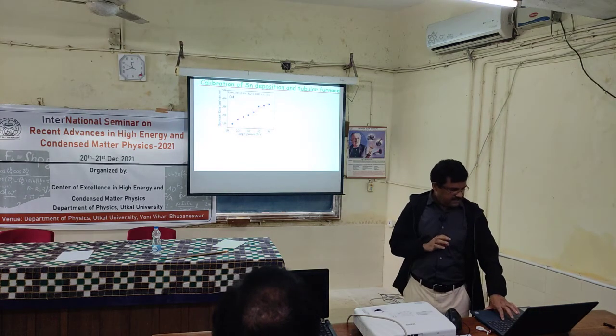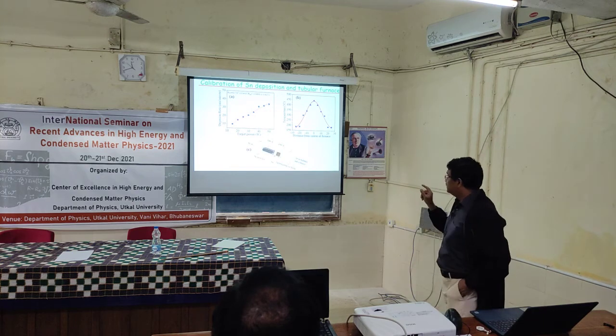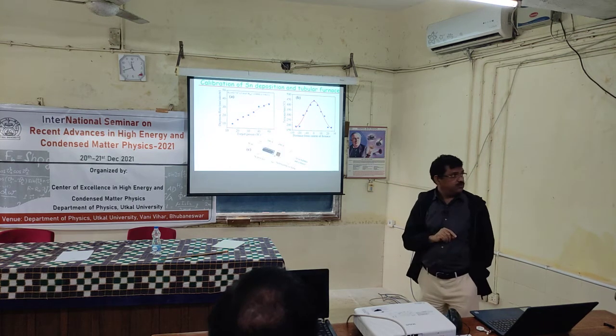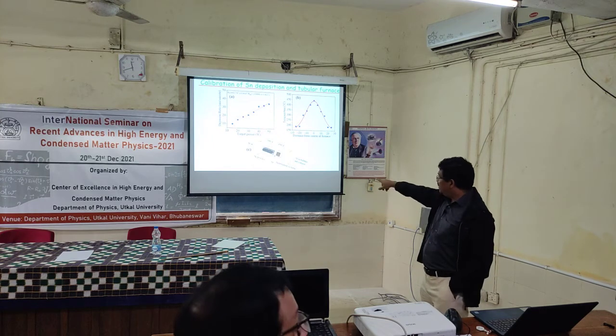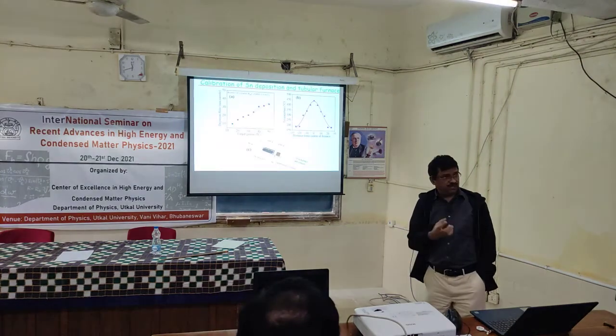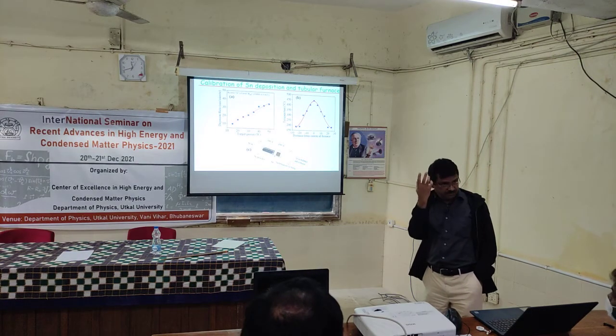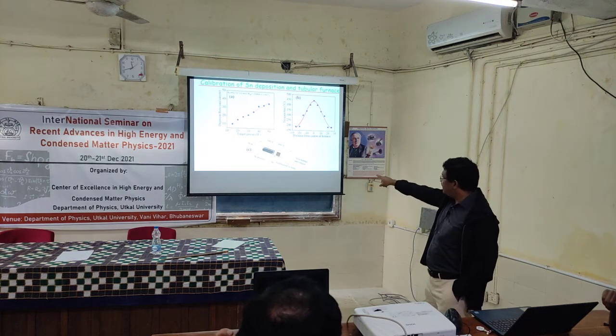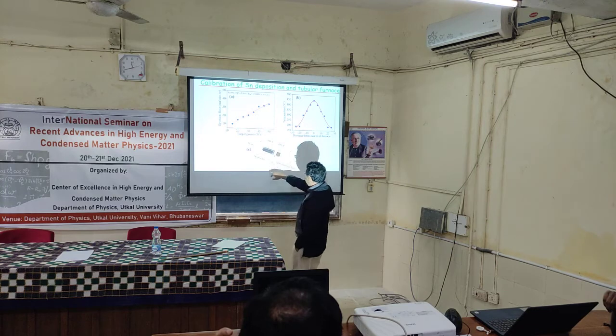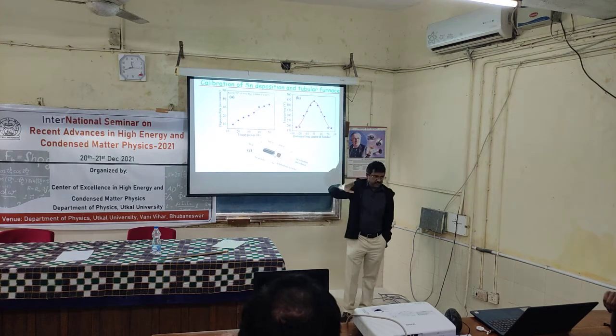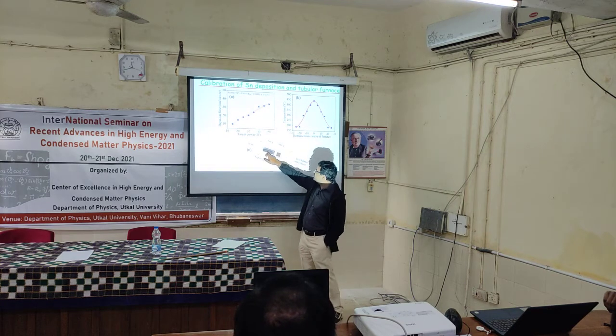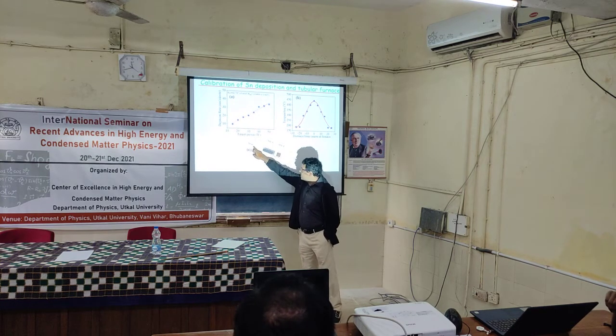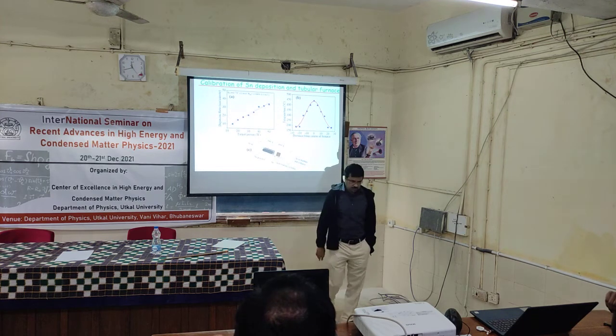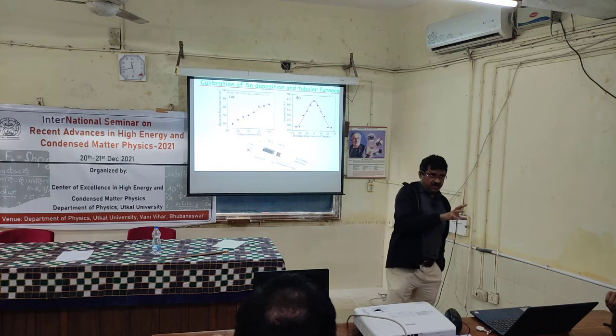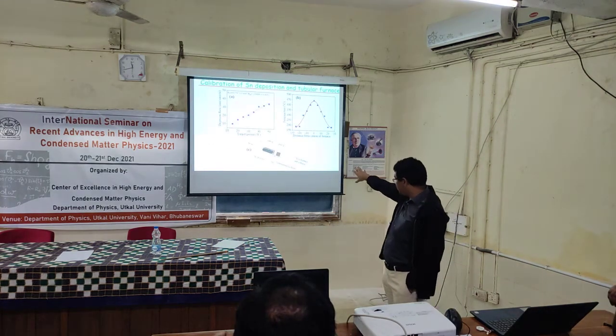So probably I will skip this, but we have just synthesized SnSe2 systems, a thin film. We just sputtered tin. You can use a vacuum evaporation system also. Take tin and evaporate it, and then use a simple system like this. You take selenium powder here, place the earlier deposited thin film here. Keep this at 300 degrees centigrade, keep this at 450 degrees centigrade, and introduce an argon flow. You will get a SnSe2 thin film. So basically, when selenium vapors go and interact with the Sn thin film, it gets converted to SnSe2.